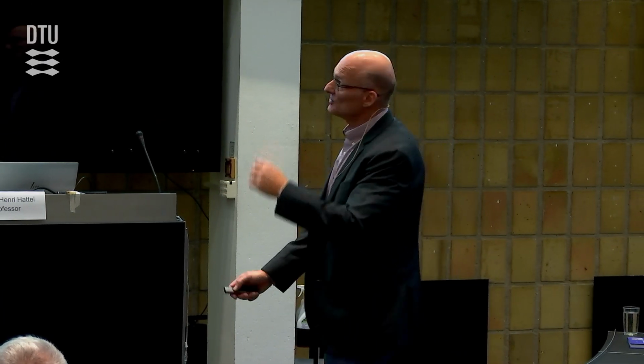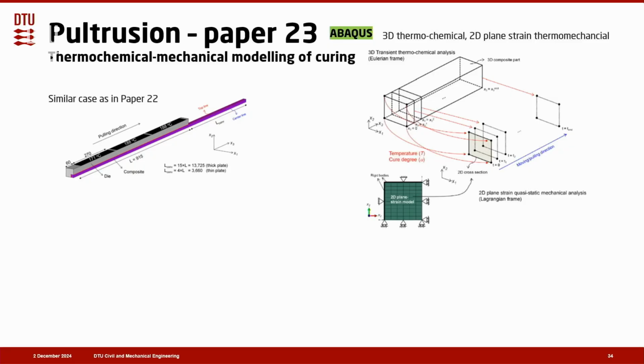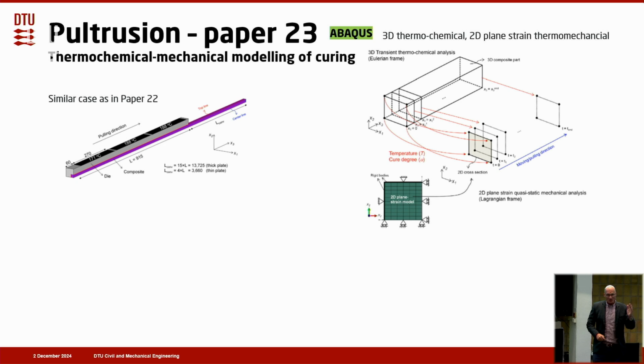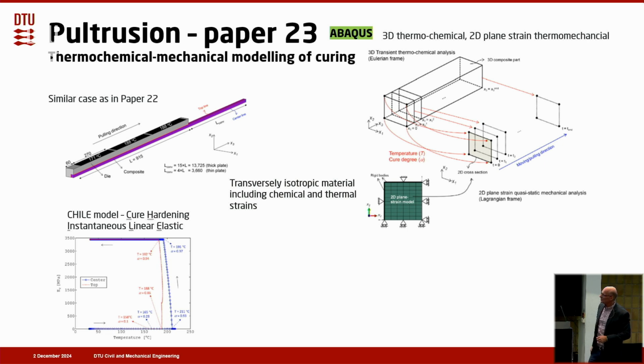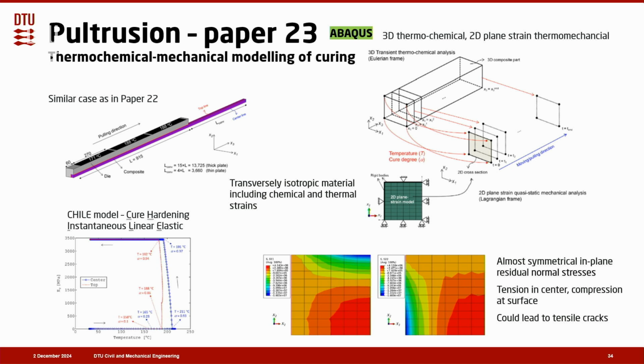Then we went to the very first thermochemical mechanical model of pultrusion in literature. Nobody ever did a thermochemical mechanical model of pultrusion before, so we took the model from before, and then we took a 2D plane strain cross-section moving through the die. And then we used the cure hardening instantaneous linear elastic model, and then we got these results for the in-plane normal residual stresses. They are almost symmetrical. That's not surprising, because it's an almost symmetrical case. And these, we have tension in the center, compression at the surface, and that could actually lead to tensile cracks in the center.